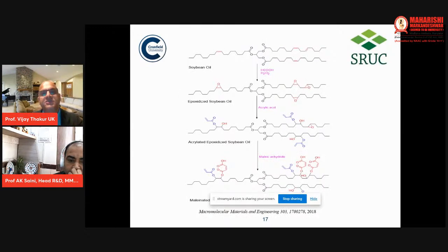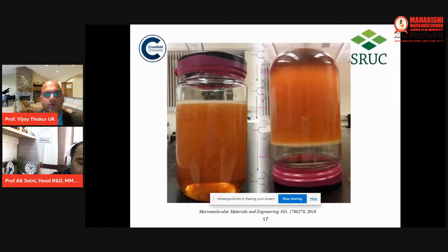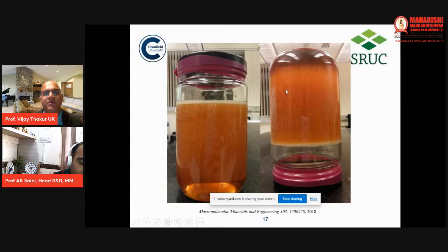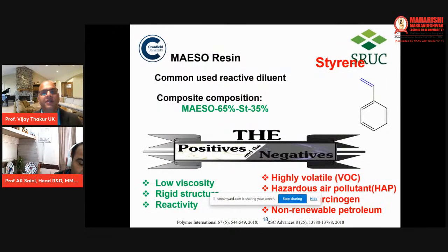And to address this issue, we have been developing both an alternative to styrene as well as to this traditional unsaturated polyester resin. Here is soybean oil, the chemistry. I won't go into more detail, but here is the final product that we got. As you can see, it looks really nice, but it is highly viscous, similar to its synthetic counterparts. So we also came across that we need a reactive diluent. Traditionally, styrene has been used as a reactive diluent because it has low viscosity, provides good mechanical characteristics, and is reactive enough to polymerize with another system.